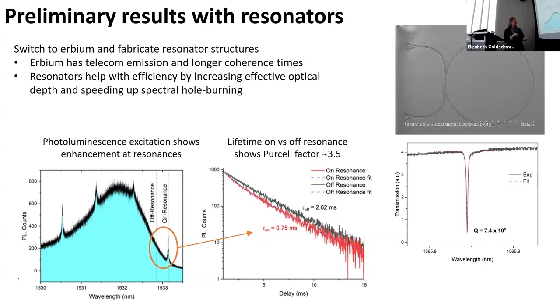And so the spectral density isn't that high. But also here, we're on chip. We're really interested in these protocols where we're going to store on the optical transition, and not use a spin transition, relatively short-lived storage, but on chip. And so in that case, we're going to take advantage of that bandwidth. Even though our spectral density is low, we can get a lot of atoms as long as we go big broadband.